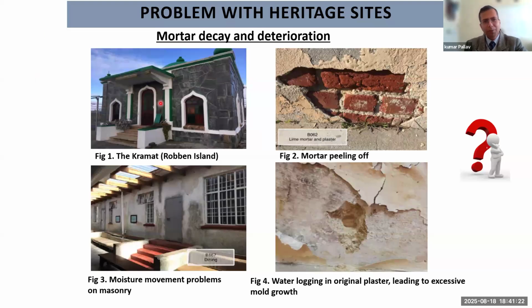So the problem with heritage sites is, if you see in this, it's Robben Island, the Karamat, which is there. And the mortars, if you see, this is peeling off from the wall because the location is close to the sea, and these are the problems which you can see. It means a moisture movement problem, because look what has happened: they have treated it with cement, PPC, etc., and the moisture absorption of lime is much better. Lime mortar is much better than your cement.